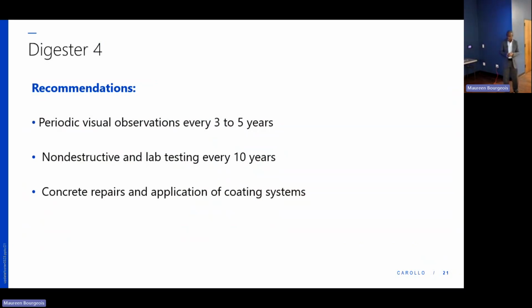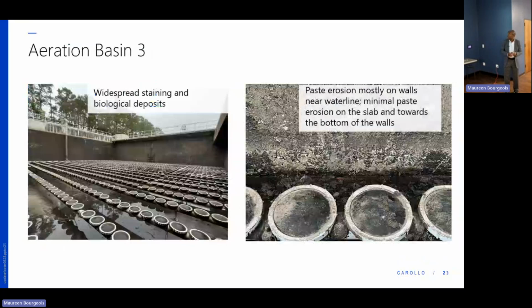That takes us now to aeration basin number 3. Again, we see the pictures demonstrating the biological deposits and the staining due to the wastewater environment. We also see above the water line, the paste being eroded, again with the bacterial activity, right moisture, right oxygen, the turbulent water, because the water is actually aerated, and we can see that erosion taking place near the water line. But towards the bottom of the wall and on the slab at the bottom, minimal or none is occurring.